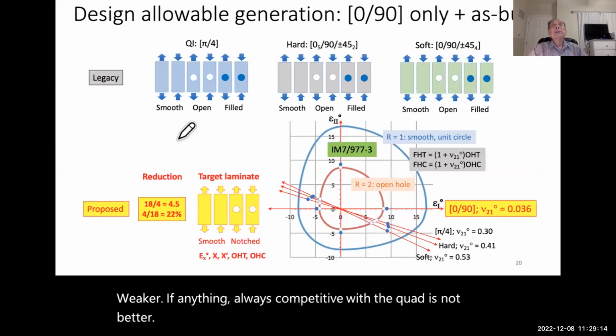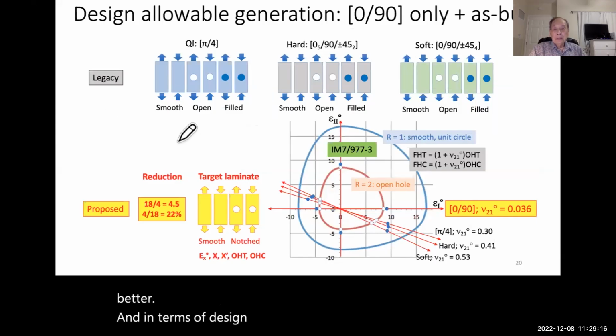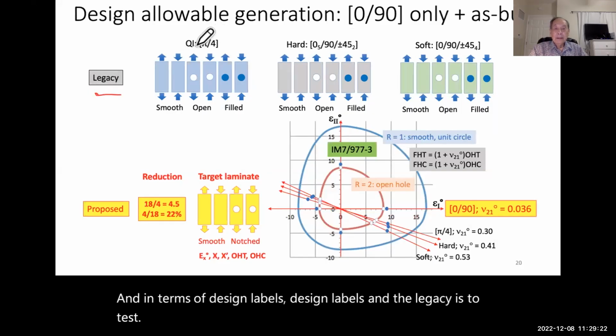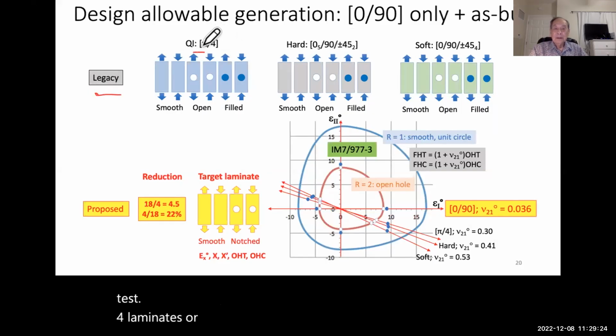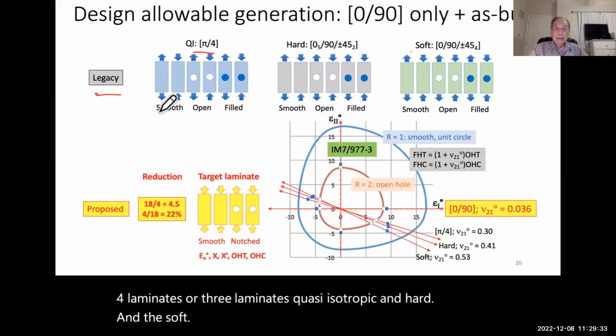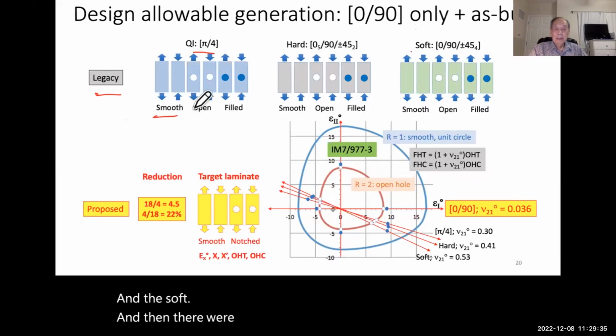And in terms of design allowables, the legacy is to test 4 laminates or 3 laminates: quasi-isotropic, hard, and soft. And then they test a smooth laminate, open hole, and filled hole.